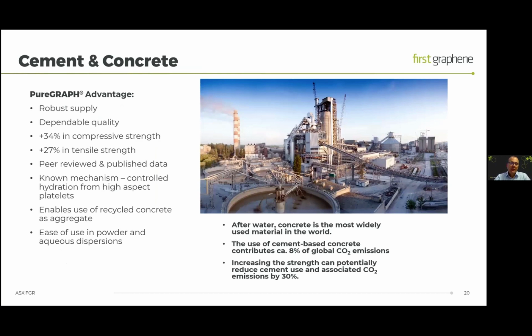Cement and concrete. Now, as Terence said, I've been involved in graphene for a long while. And when people 10 years ago started to talk about putting graphene into cement and concrete, this seemed kind of improbable. But we're seeing real opportunities here because the effect of adding graphene is effective at such low dopant levels. If we look at the concrete industry in terms of the big picture, it's an immense industry. After water, concrete is the most widely used material in the world. And the use of cement-based concrete contributes somewhere between 6 and 8% of global carbon dioxide emissions. So potentially increasing the strength of these materials by, say, 30%, you have the opportunity to reduce the amount of cement and concrete which is deployed, and therefore reduce the carbon dioxide contribution of the cement.